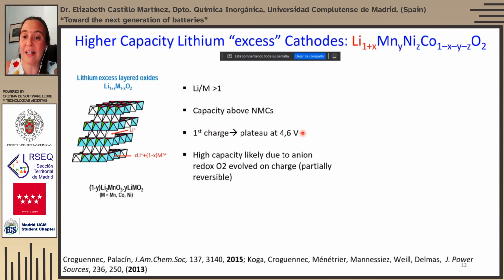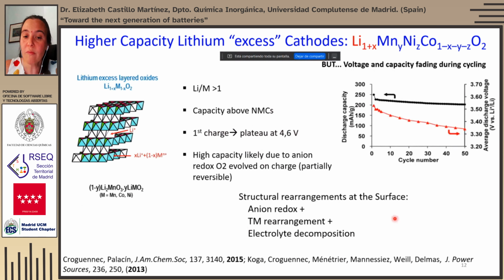in the surface of the particle, there is some oxygen loss, I mean, anion redox. And this leads to transition metal rearrangement. And because there is a transition metal rearrangement, the voltage of reaction changes. So what is observed in these materials is that the capacity, the discharge capacity, as well as the average discharge voltage goes down as we are cycling. So despite these materials having very high capacity, they still have some issues that keep them far from commercialization.